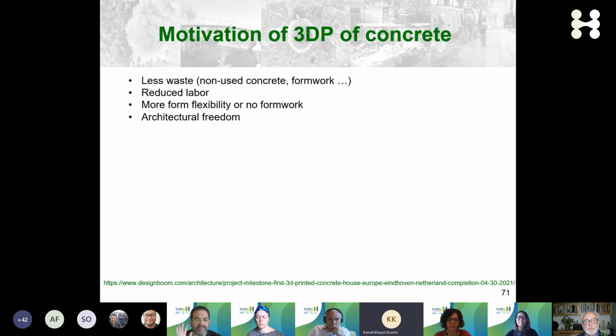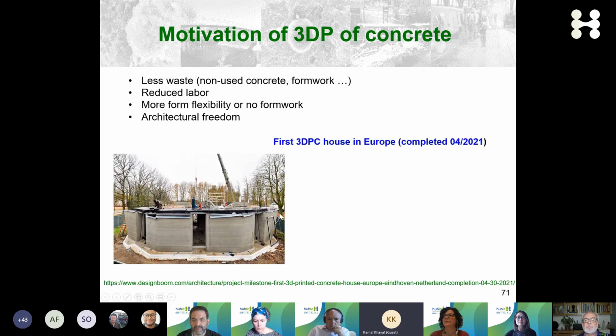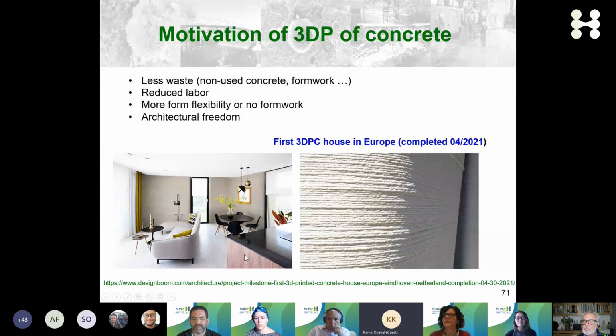And I know you're very interested, and there's a mega trend in the world for automation in construction, so I couldn't leave that alone. So I'll just say that as a follow-up of the development of high-performance concrete with adapted rheology, is how can you adapt the rheology so much to a material that you can pump it and extrude it and then build it layer by layer to construct some structural elements. So this is 3D printing. And here I have a photo from a website of the first house that was constructed in Europe using 3D printing. And you can see that it looks like a very nice open space and nice surface texture. So these are about 10 to 15 millimeter layers constructed layer by layer. And obviously there are a lot of advantages in this new technology that is taking off really around the world.